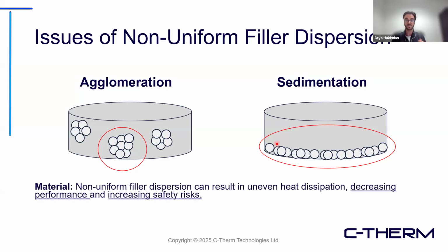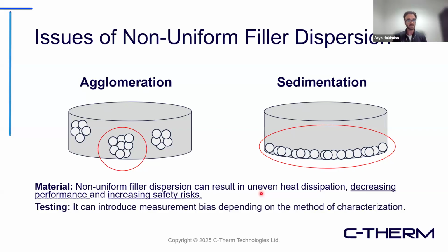Well, from a material perspective, you can imagine if we are working with, let's say, a thermal interface material, this can result in uneven heat dissipation and hot spot buildup. That's a safety risk for things like thermal runaway, for example. But from a testing perspective, it's also something that we need to consider, because depending on which method is used, this can introduce some variability in your results. The reason for this is that, depending on which technique is employed, each method will have its own set of underlying assumptions. Some methods are directionally dependent in their output, others are more of a geometrical average.